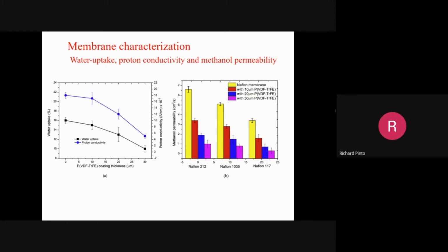So that is the key. You reduce the methanol permeability in the membrane without really reducing proton conductivity significantly. So that is what we have achieved in this slide. And the optimum is of course 10 micron. If you use 20 and 30 micron, conductivity drops down. So this is the point.